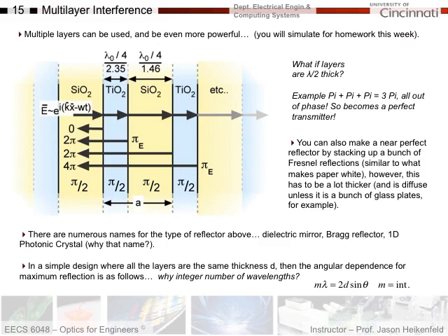And so we have multiple layers of silicon dioxide, titanium dioxide, silicon dioxide, titanium, etc. Okay? And each of these are designed to be a quarter wavelength thick, meaning that it's the wavelength of light in vacuum divided by 4 divided by the refractive index. Remember, the refractive index shortens the wavelength of light. So if I want to make this a quarter wavelength of light, the thickness has to be calculated as follows. And I make it a quarter wavelength for the silicon dioxide as well. Notice the silicon dioxide is thicker than titanium dioxide. That's because its refractive index is lower. This higher refractive index reduces this number, so it has to be thinner to be a quarter wavelength thickness.